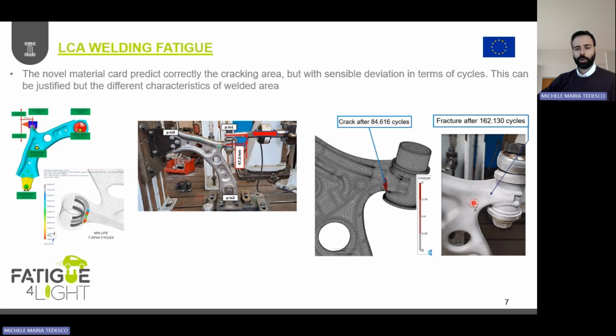So from the location of the cracking, we were able to predict properly the starting of the crack, while we noted a big difference in terms of crack starting time. In the simulation, we predicted that the crack starts at 84,000 cycles, while in real life, the starting of the crack was over 160,000 cycles.